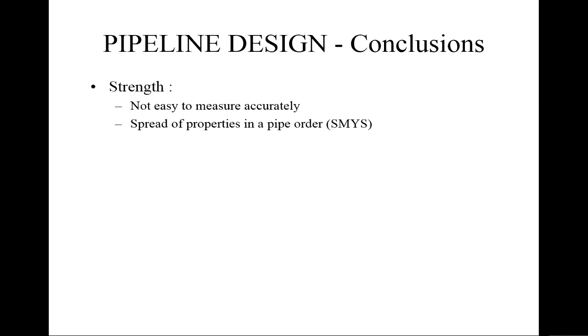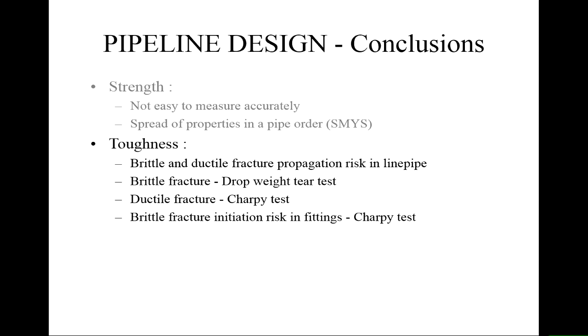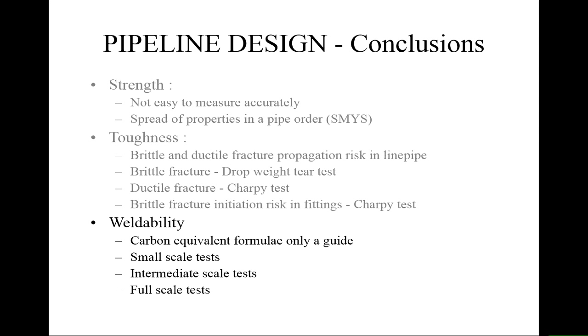Nearly finished. So just for conclusions on design, strength is not easy to measure accurately. There's a spread of properties, so we go for the specified minimum yield stress. Toughness, we can measure for brittle and ductile fracture propagation. We can use drop weight tests for brittle and Charpy tests for ductile fracture, and we use a Charpy test for measuring fittings. And weldability, carbon equivalent formulae are often used to assess different materials, but they're only a guideline. They don't tell you about the welding procedures used and how that affects things. So you have to do tests.